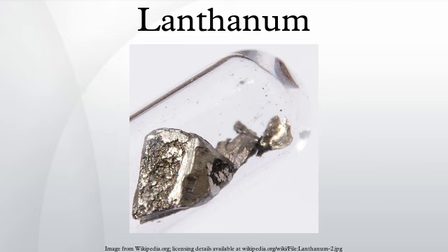Cerium-doped lanthanum bromide and lanthanum chloride are the recent inorganic scintillators which have a combination of high light yield, best energy resolution, and fast response. Their high yield converts into superior energy resolution. Moreover, the light output is very stable and quite high over a very wide range of temperatures, making it particularly attractive for high-temperature applications. These scintillators are already widely used commercially in detectors of neutrons or gamma rays.